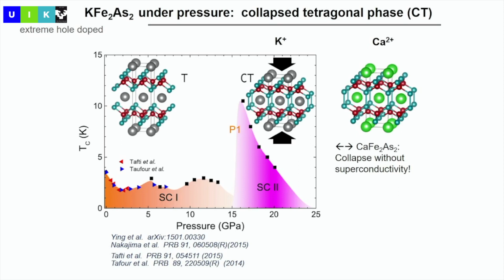Now, what is interesting about this material, this is temperature as a function of pressure, is that if you press the system, at least this is what was reported some years ago in experiment, one would observe superconductivity really going up at a given critical pressure of 15 gigapascals with a rather large TC with respect to the TC that you have at ambient pressure. And the question was, what gives this shooting up of the superconductivity, and whether these correspond to superconductivity of different nature.